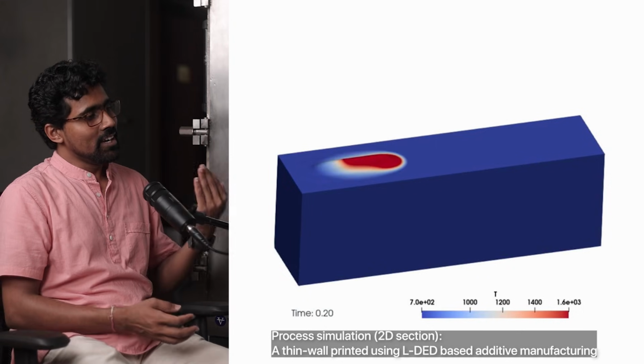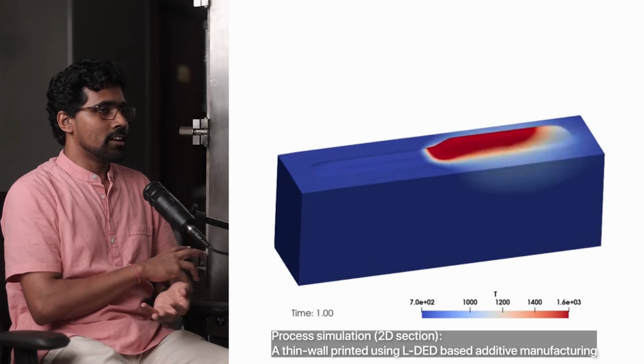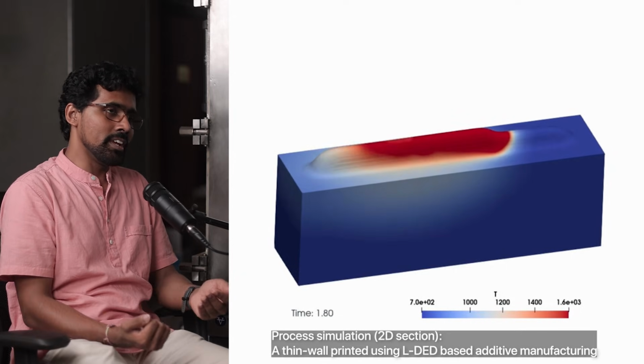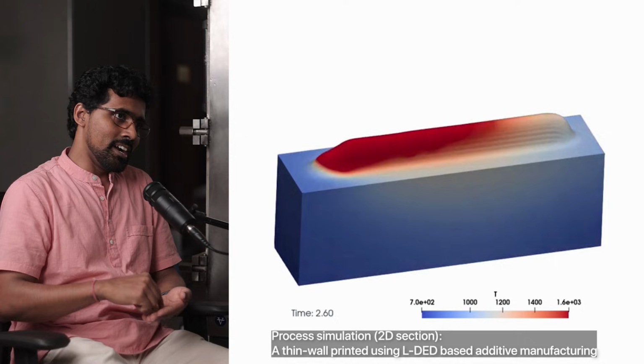So it's happening in fractions of seconds. One thing that people do is use high speed IR cameras to capture what is actually happening: how the liquid formed, how powder is falling, and what sort of fluid flow, because powder is coming with some velocity and it's a liquid. Also, there are surface tension based flow, gravity based flow, lots of things happening there. If you want to understand solidification, since we do not have access to this kind of in situ analysis, we took the approach of simulations. We created a model which simulates the heat transfer, the fluid flow, and the solidification that happens as we deposit powder and scan the laser.